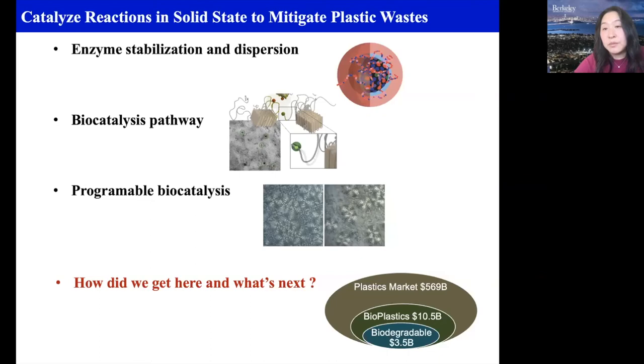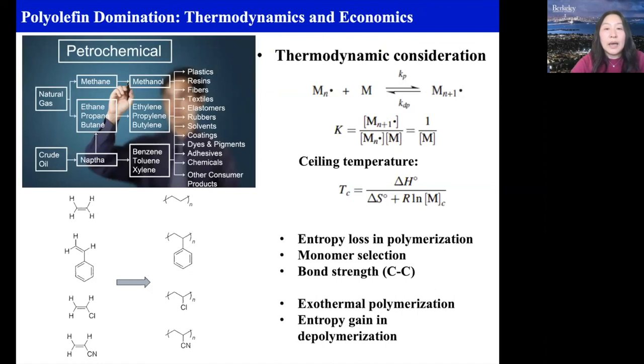So this is just sort of a propaganda slide that tells you why polyolefin is so abundant. One is that it really relates to the readiness of petroleum chemistry. In the petroleum industry, you see those monomers are very easily produced and they can just be converted into polyolefin. From the polymer chemistry point of view, it's very easy to polymerize them because you form the C-C bond and the reaction is exothermic, so you can stabilize the entropy you lost during the polymerization. So the C-C bond is so much more stable than the ester bond I just mentioned to you.